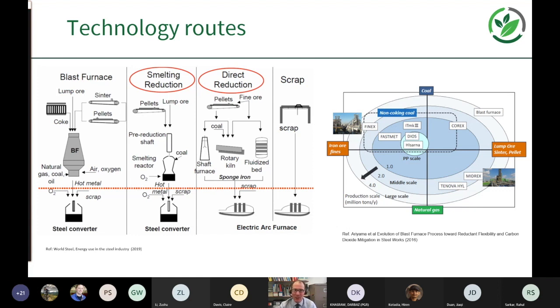Then we have the direct reduction, which uses iron ore directly with gases. They could be syn gases, or hydrogen possibly, or coke oven gas, depending on the technology, and there are very well established technologies in place in the industry for producing directly reduced sponge iron. So in the solid form, it's a lower temperature. That's why the energy emissions associated with it are lower. It tends to be used to improve the quality of the final product from the electric arc furnace. And then, as we described previously, we've got scrap-derived steel production from the electric arc furnace. And we'll cover some of these in a little bit more detail later.